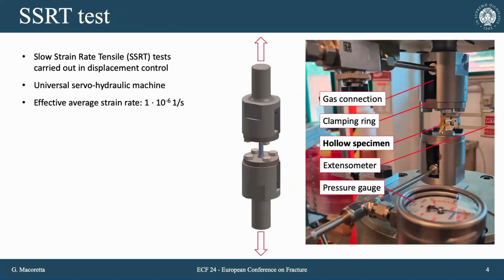This is the specimen. This slow strain rate tensile test is carried out in displacement control with a displacement of 0.1 micron per minute, per second, let's say. And so we obtain an effective average strain rate of 1 times 10 to the -6 per second. So it's a very slow tensile test.